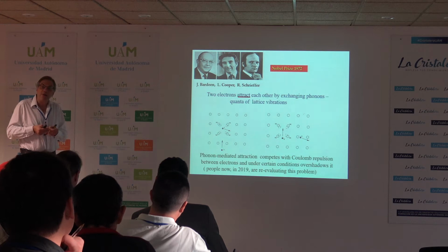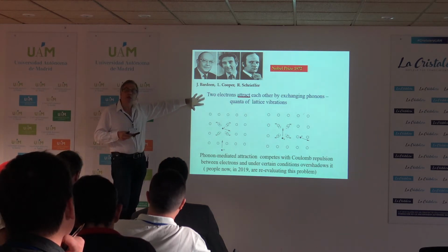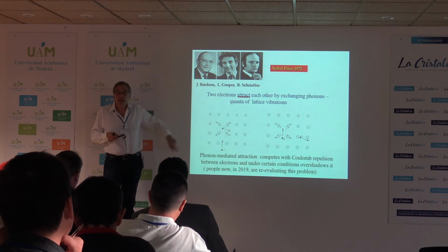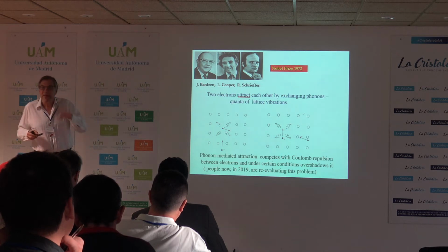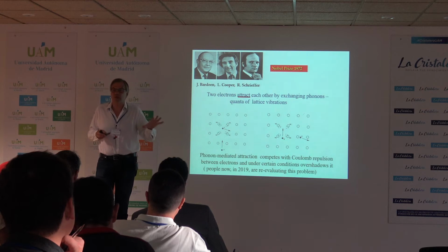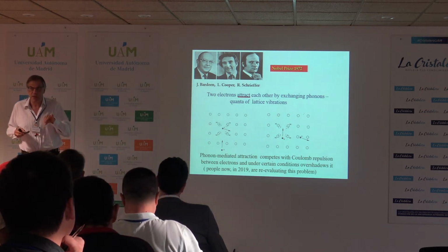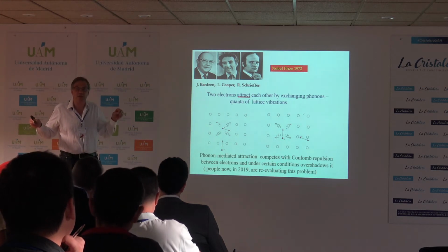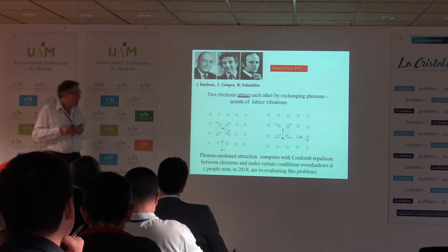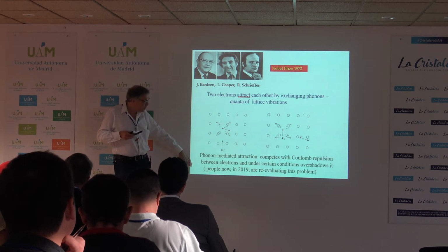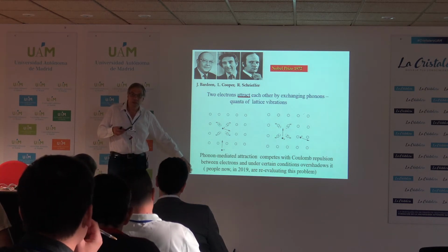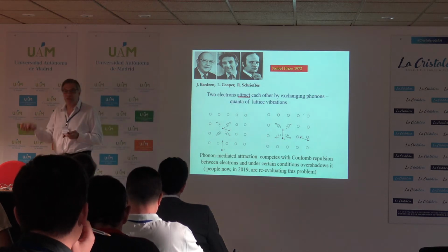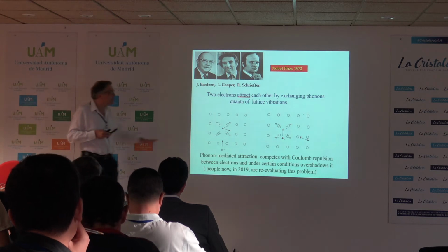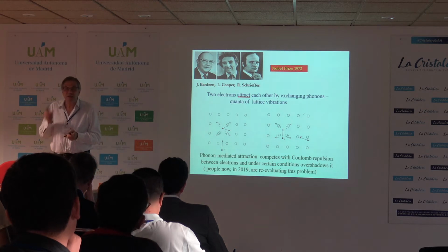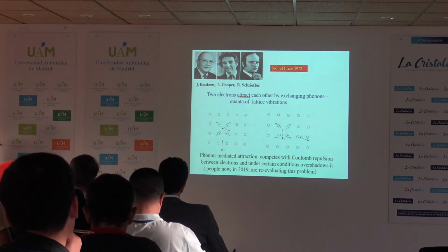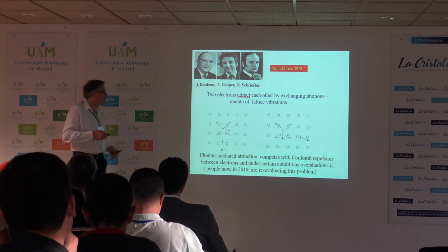And the question that was somehow put under the rug is, yes, there is attraction due to phonons, but there is also repulsion due to electron-electron interaction. It was somehow believed for years that at the end of the day, you can forget about electron-electron interaction to first approximation, and electron-phonon interaction is sufficient to give you superconductivity. Which is true when there is a big separation of scales, for example, when Fermi energy is much larger than the Debye frequency. Interestingly enough, it was done in '57, and fast forward to 2019, this year, people are now reevaluating the story for the case when Fermi energy and the Debye frequency are of the same order, and it's not entirely clear whether this mechanism gives rise to superconductivity in that case, because of Coulomb repulsion, which acts against electron-phonon pairing. So the total story may be a little bit more complex than originally thought.